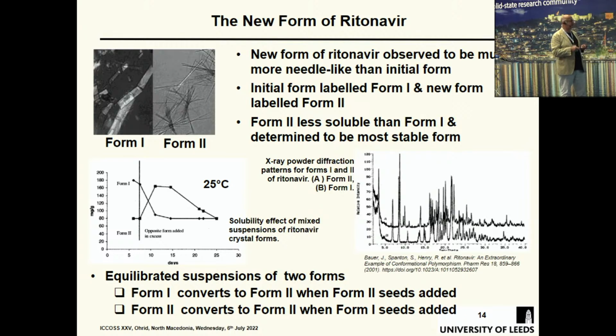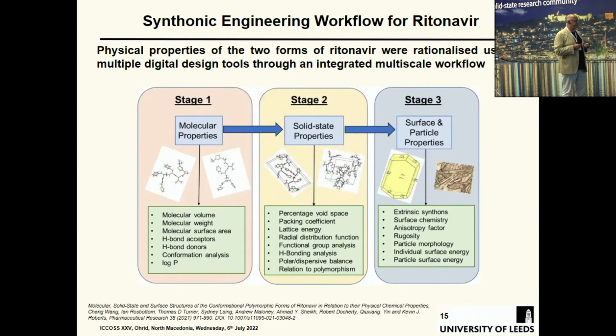And these are some of the pictures. What they found, they did slurry experiments: make a form 1 solution, make a form 2 solution, then add the opposite seeds in, and it always ended up with form 2. Distinct powder patterns. And broadly speaking, the morphologies were elongated, plate-like in form 1 and needle-like in form 2, and we'll go back to that right at the end. But basically, you always get form 2.